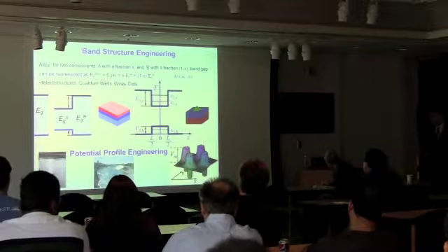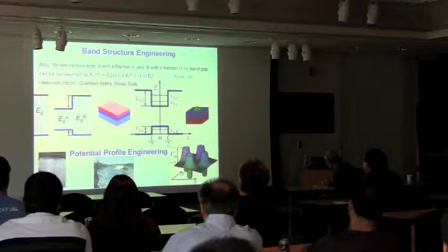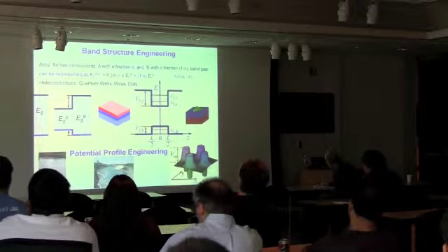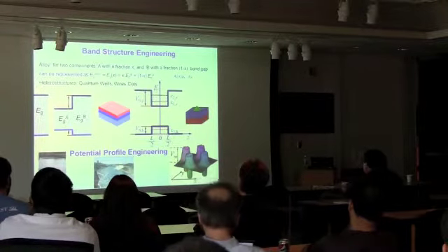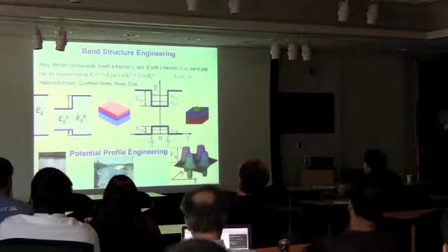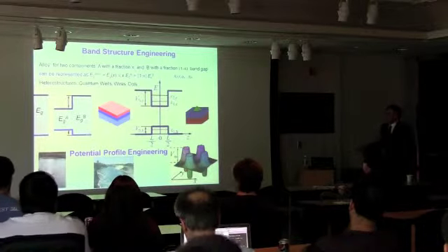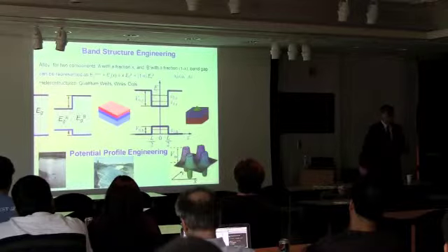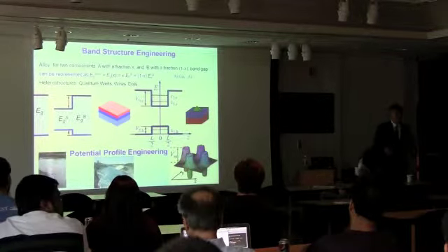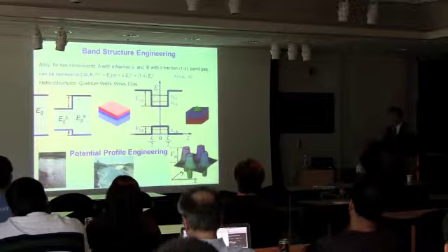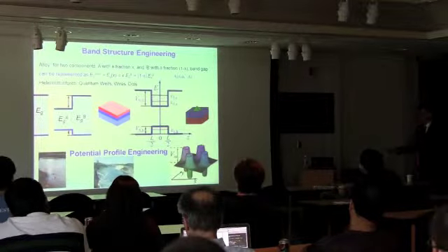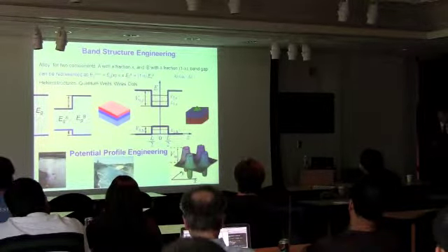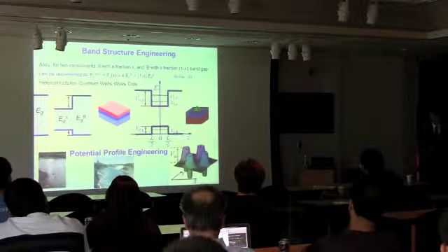The advantage of this band structure engineering is that now you can change the material of the matrix where you put the dot, you can change the material of the dot, and you can change the size of that dot. Doing all this, you can change the distance between the levels in these dots. So you use it for devices. And this is widely used. I just remind you that it's very popular in engineering to produce new materials.